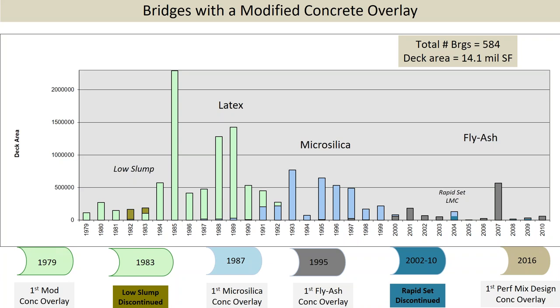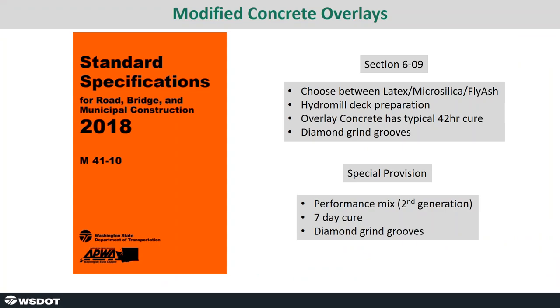And then we are doing now some performance mixes, which are similar to what a brand new bridge is. Currently in our specs, what we would allow is we have a recipe mix for latex, microsilica, and fly ash, and the contractor can choose any one of those recipes. They generally like microsilica and fly ash because the mixes come through a ready-mix plant. The latex requires an on-site mobile mixer, which most contractors don't like these days.